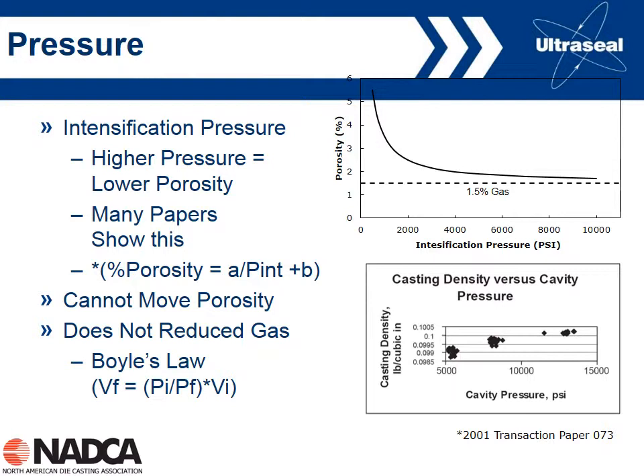with an increase in pressure. One thing we do need to keep in mind, however, is that when we apply pressure to any liquid, whether it's liquid aluminum, a hydraulic system, or just water, the pressure in the liquid is the same at any point in that liquid. What this means is that we can't move the porosity around from pressure alone. We can reduce the size of the pore, we'll talk about that in a few minutes, but we can't move it around. So if we have a pore that's close to a critical area, we can't move it away from that critical area from pressure alone. We talked a little bit about this in the first webinar, where Boyle's law shows the impact pressure will have upon the volume. The volume depends upon the initial pressure divided by the intensification pressure. So we can reduce the size from pressure, but we can't change the location from pressure.